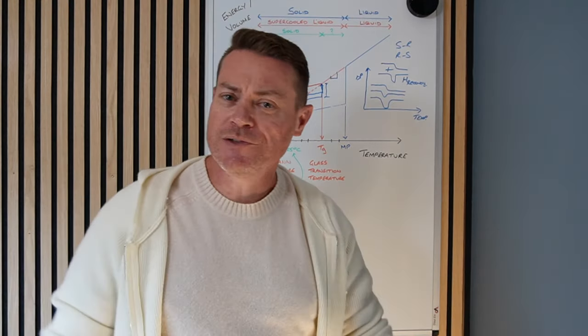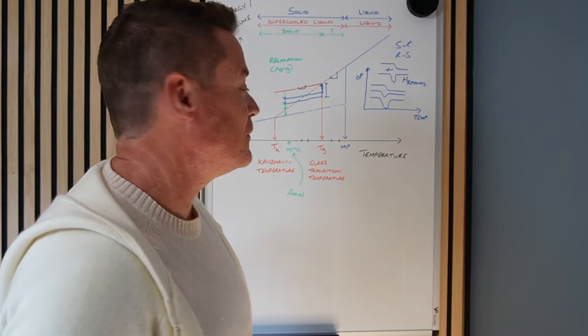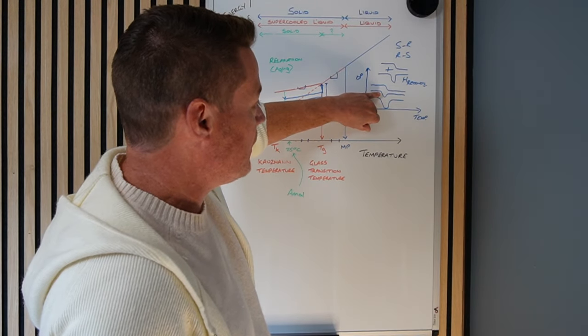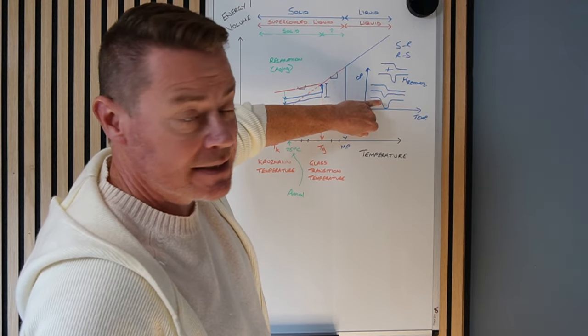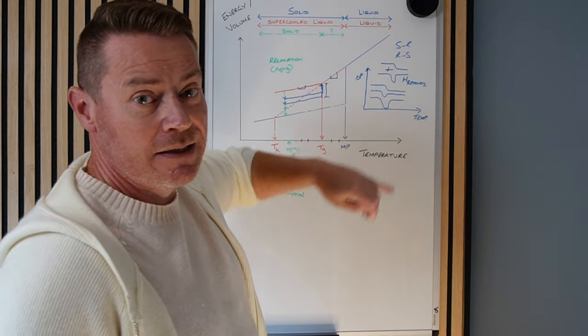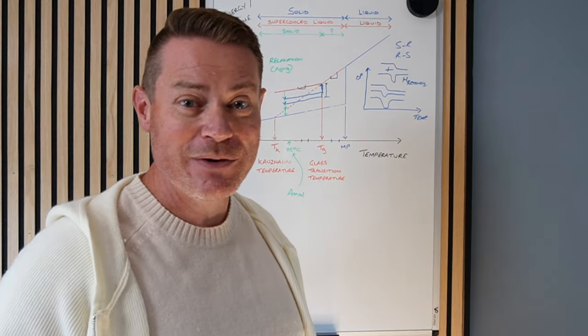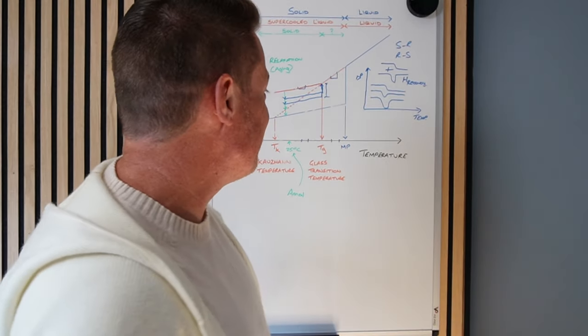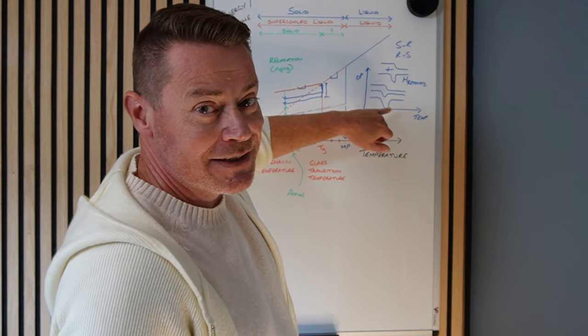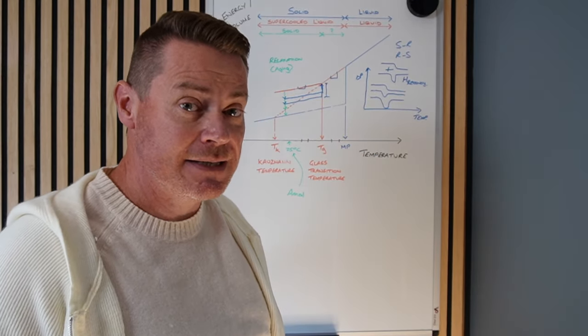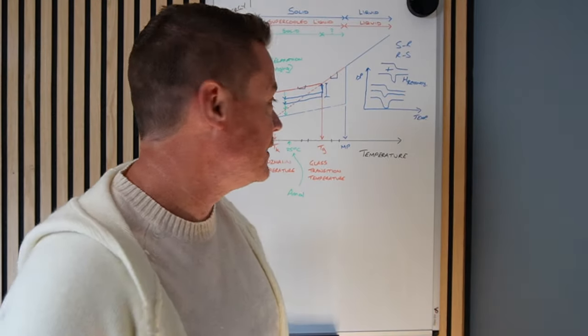This leads to a couple of important points. First, you might notice that if this peak is getting bigger with time as the amorphous material is relaxing, we can use these data to measure the rate at which the material is relaxing. We can measure the area under these curves, and from those areas calculate the rate at which the material is relaxing. I'll talk about that in a separate video, as it's too complicated to get into here.